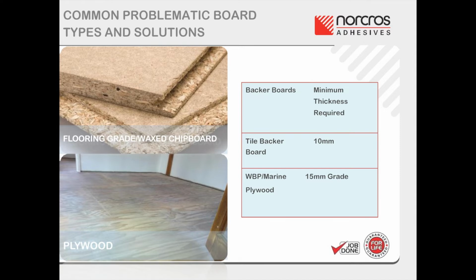The same problem with deflection and expansion due to atmospheric changes occurs when tiling to chipboard as with plywood. Waxed chipboard should not be tiled directly onto. A plywood overlay or tile backerboard should be applied and mechanically fixed to the chipboard at 300 mm centers. Using plywood or appropriate backerboard will also strengthen the floor sufficiently to use polymer modified adhesive over the top.